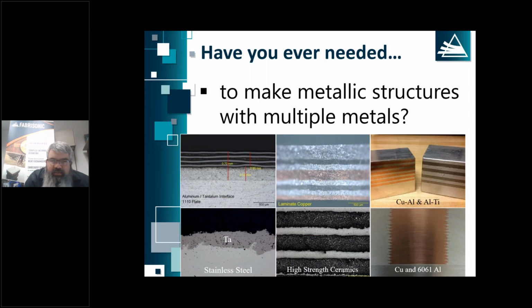Some applications of that, the aluminum copper is used all the time for thermal. We mix that combination to kind of get the lightest weight, highest thermal conductivity structures possible. On the top left, we have layers of tantalum, aluminum, and I believe tungsten. That's actually used for radiation shielding for satellites in high radiation environments. That's something we do a lot of. Customers provide us with a template of a radiation shield that has different metals with different atomic numbers, Z numbers, and this allows you to create a very effective shield at a very low weight.